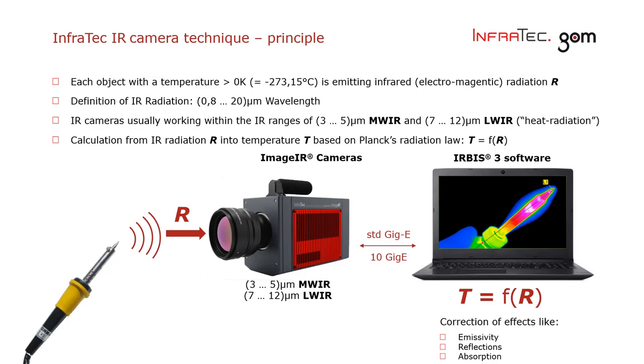So the calculation from the infrared radiation which is received by the camera into the temperature is based on Planck's radiation. So we have a direct correlation of both the temperature and the radiation. The sketch is showing an infrared camera which is just receiving the radiation and turning these values into digital values which are transferred to a PC. So these cameras are working either in the mid-wave or long-wave range, and the data are used for each pixel by Planck's law to be calculated into a temperature. Also, we can do some corrections within the software, which is taking into attention the emissivity of the material of the sample, some reflection from the environment, and also some absorption which can occur between the object and the camera.